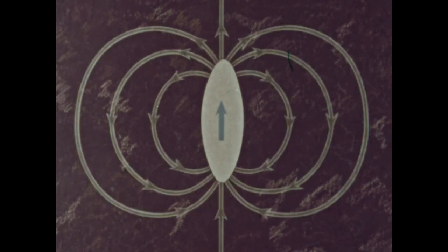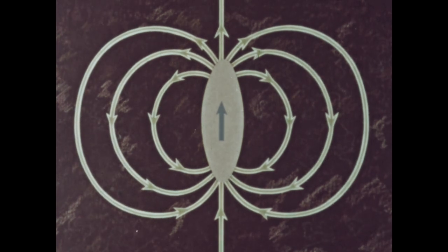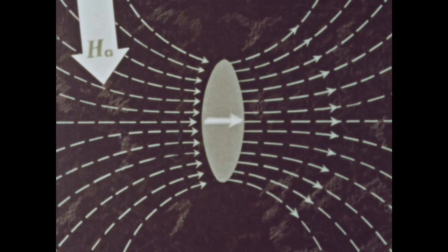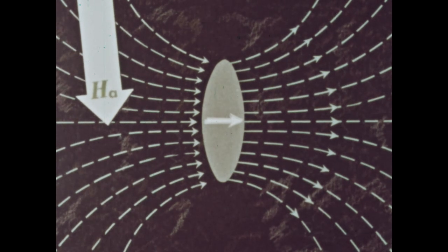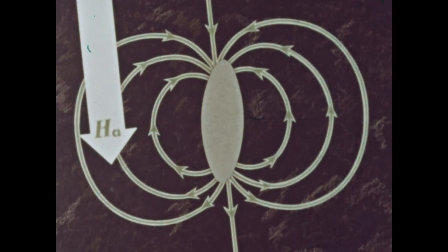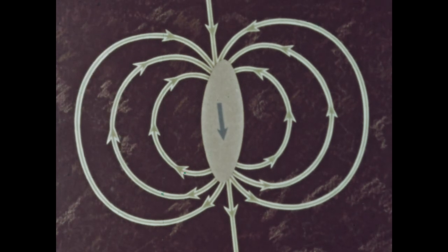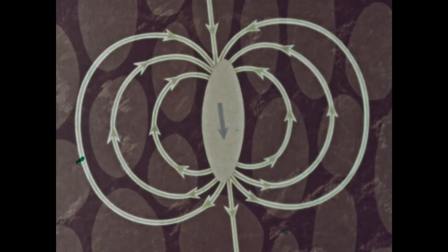When the magnetization is along the long axis, the magnetostatic energy of the particle is a minimum. To change the magnetization by rotation, the field must overcome a very large magnetostatic energy barrier, which arises when the magnetization is along a short axis. Compacting such fine particles makes a good permanent magnet.